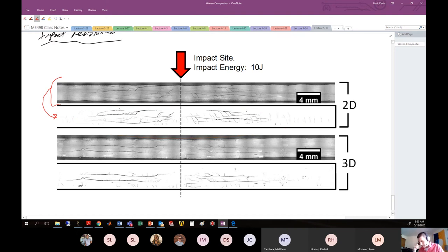All right. So if you compare the skeletonized damage in the 2D versus the 3D, you get some interesting results. You see in the 3D, a lot less transverse shear cracks, right? So here are some transverse shear cracks, and so on and so forth. You have delaminations that are occurring here, here, here, here, etc. In the 3D composites, similar idea, right near the impact site, there are these transverse cracks that are inside the piece that maybe disrupt the load carrying capability in the plane slightly. And you also have long delaminations that form.